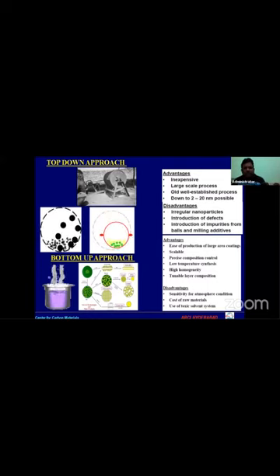The advantage is that it is very less expensive. Any small lab can have a ball mill or any milling machine. You can reduce the size, and you can do large scale processing. It is an old but well established process. You can get 2 to 20 nanometer, but the disadvantage is that you don't have control over the size, the particle size distribution, and the morphology. Irregular nanoparticles and the introduction of defects are possible. All those things are possible.